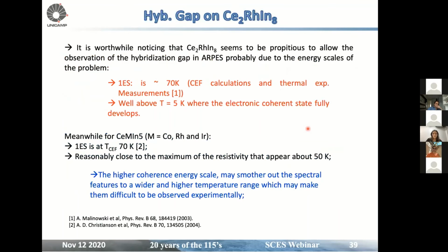And so we would like to notice that it seems we have a propitious scenario to see the hybridization gap for Ce2RhIn8, because of a simple explanation: the first excited state in Ce2RhIn8 is about 70 K. That is from crystal field calculations and also thermal expansion measurements from Malinovsky. And that is well above the coherence temperature. Meanwhile, in the CeMIn5 115s, the first excited state is around 70 K, reasonably close to the maximum of the resistivity, which in that case is 50 K.